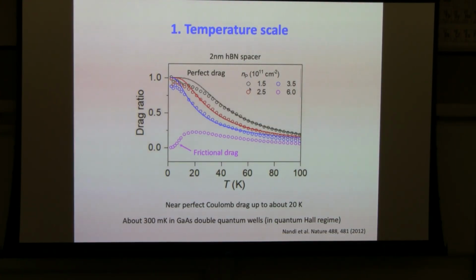So let me think. What I should do is plot the exciton current in the system, better to plot the drive current, to see whether, even in the two-terminal measurement, we can get any signature of exciton superfluidity. It's limited by the contact resistance of the excitons, which is pretty large. So I doubt that, even if we plot the drag current, we can spot a BKT transition. Probably not, I would say. So we actually need to do a 4-terminal exciton transport measurement in order to do that, which we are trying, but no success yet.